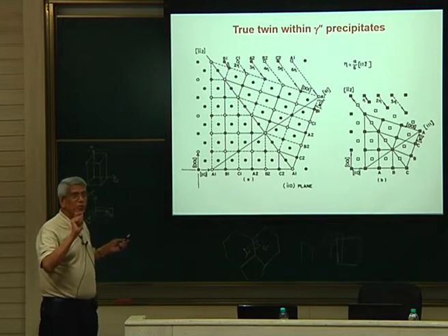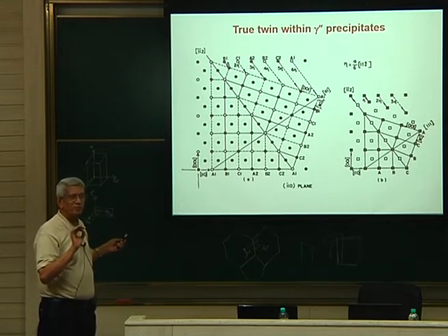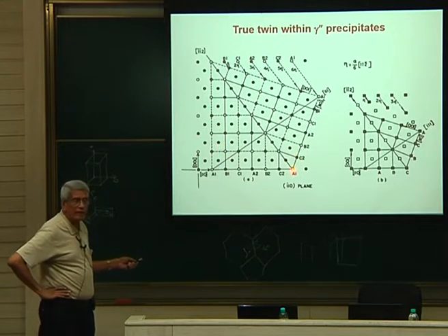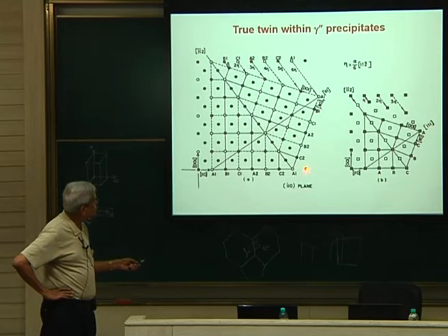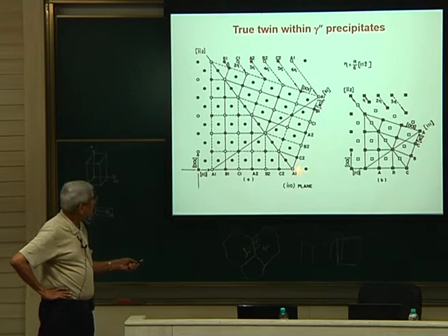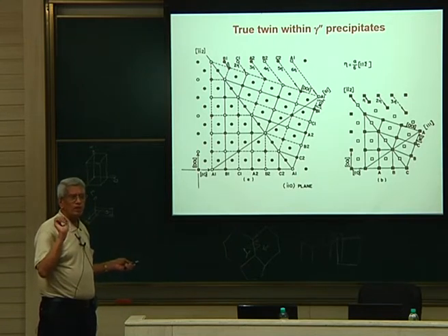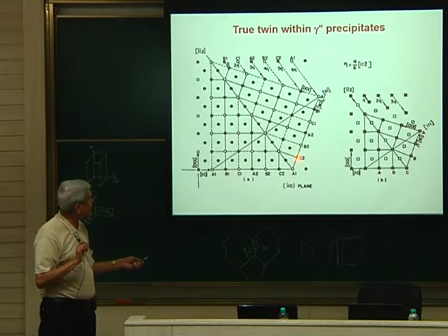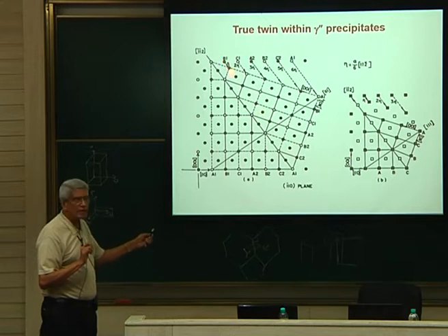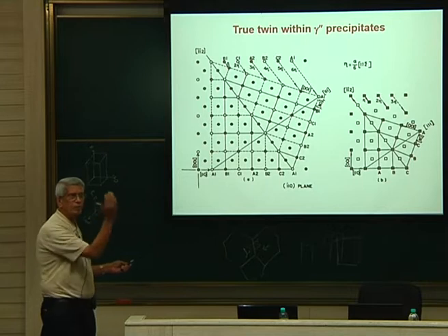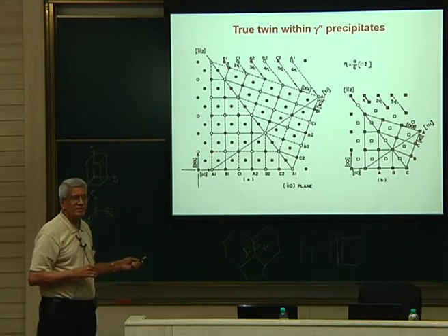What I am talking about is how we can consider twinning. This is an ordered layer. The next atom position should come here. You know that a stacking fault happens by movement of a partial, a/6 <112> direction, moving an atom from here to here. If I make a partial move in this direction, not only are all the atoms in this layer shifted, all the atoms above the layer are also shifted, correct?